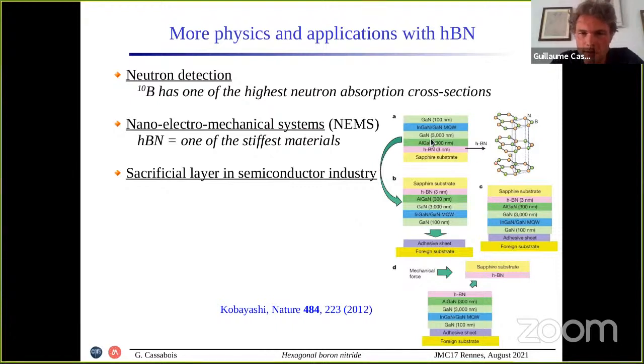This scheme is a little complicated, but basically people start from a sapphire substrate, grow a thin layer of HBN and then the device, then flip chip the structure onto a foreign substrate, taking advantage of the weak interaction between the layers to remove the growth substrate. Basically, we can reuse the growth substrate for further epitaxial processes by using this HBN as a sacrificial layer.